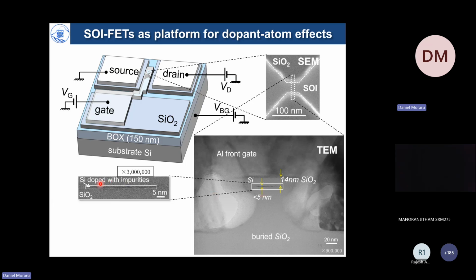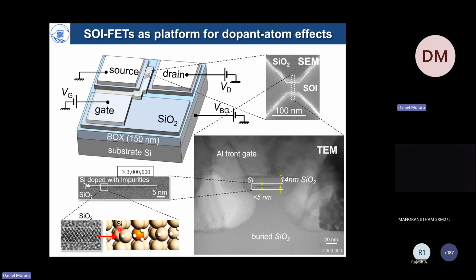And you can see here a high-resolution TEM image which shows the crystalline matrix of silicon embedded into the amorphous silicon dioxide. Now, even this kind of small dimensionality capability is not so interesting for us. What we are interested in is the functionality that we can obtain from substitutional dopant atoms or impurity atoms and not from silicon atoms. So we should understand very clearly that we are actually building these big devices, microscale devices with nanoscale or hundreds of nanometer size channels, in order to capture the atomic level functionalities.